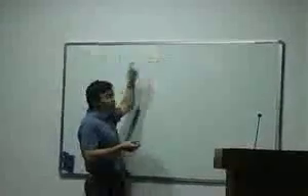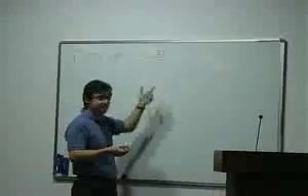Well, you know that at the glass transition temperature, tau 0 is a microscopic time, let's say picoseconds. So log of tau alpha divided by tau 0 is a universal quantity at Tg, just because the glass transition is defined as, for example, the temperature at which tau alpha is equal to 100 seconds. So this quantity is the same for all supercooled liquids at Tg.